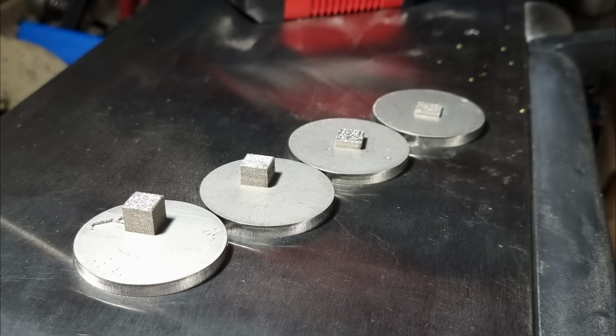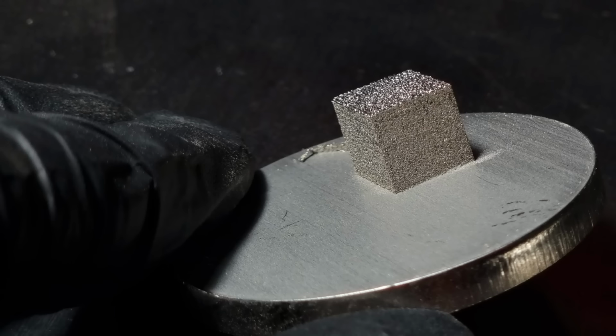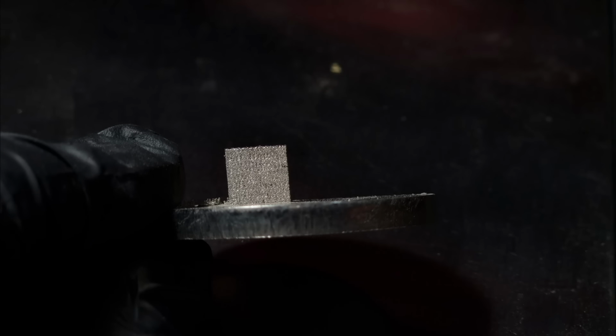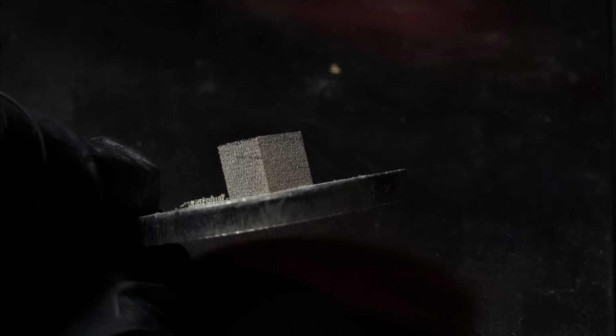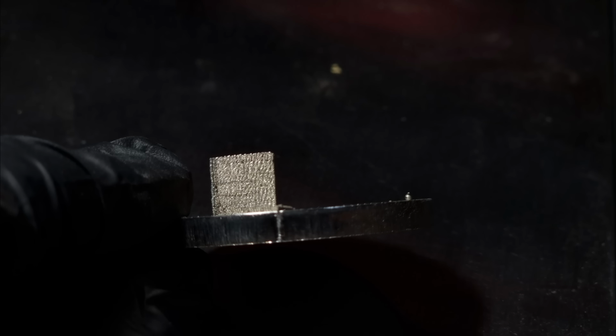Areas where the path for heat would be constrained would still suffer, but that was in the too hard basket for now. The first cube took around 4 attempts before I actually succeeded, mainly owing to the issues I mentioned previously involving the water chiller interfering with the FPGA. It wasn't much to look at and there was a clear amount of porosity, but it was a milestone complete.